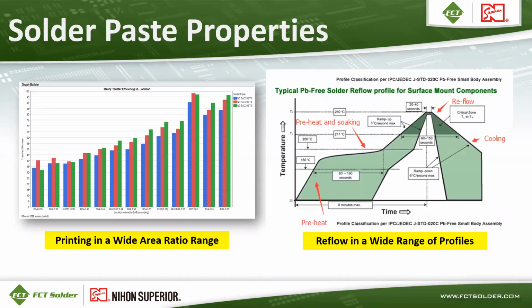The other thing we'd want a solder paste to do is to be able to reflow in a wide range of profiles. We know some automotive electronics are fairly thermally demanding when it comes to the surface mount process. It's important to be sure the solder paste can handle maybe a long soak or a higher peak temp or a longer time above liquidus and still give you a quality solder joint without building a thicker intermetallic layer.